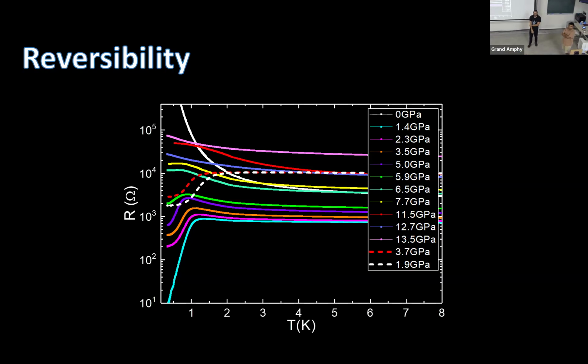And no, we never go back to this superconducting side, but I do think it's somewhat reversible. The TC is not exactly the same. It's even a bit higher. When you take a look at the 1.9 compared to the 1.4, the TC is a bit bigger. Yeah, somewhat improved superconductivity even, but it's hard to tell with not many experiments.